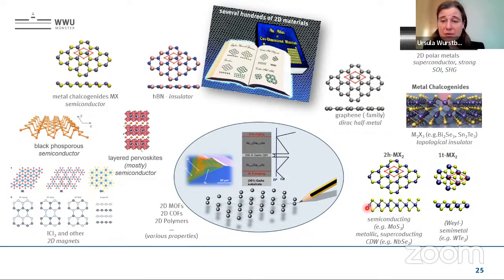So you see here, for instance, we do not have a purely atomically thin crystal structure. Here we have a triple layer as the smallest unit, meaning we have some out-of-plane bonding, but it's still really less than 1 nanometer thick. And with that, I would say it's still a van der Waals or two-dimensional crystal, because the next layer would be bonded by pure van der Waals forces.